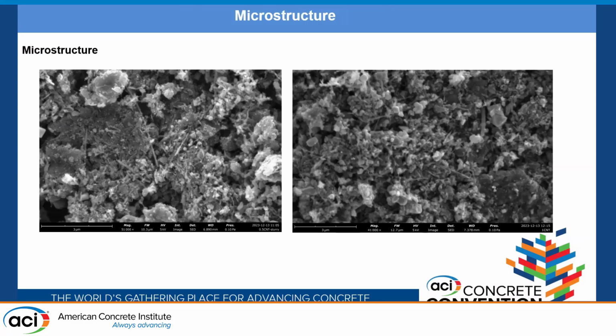That's where we really broke the sample and started to look at it under the SEM and found out the largest particles that they grew out of the chamber are really microfibers. It's not CNT anymore. It probably has close to about 100 nanometers in diameter. And again, this is very preliminary. For the next batch, we're going to go back to the smaller diameter CNT and keep doing the experiment.